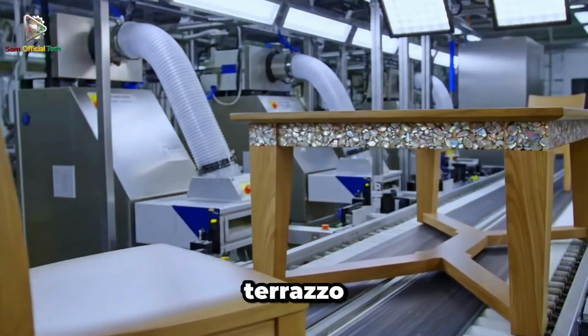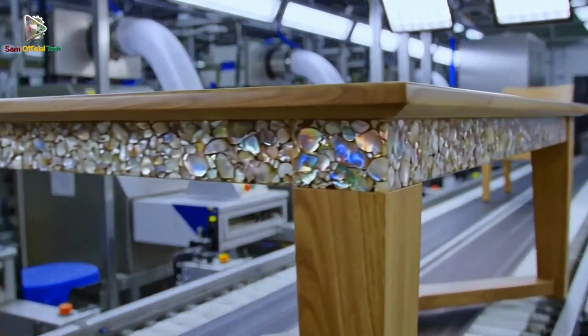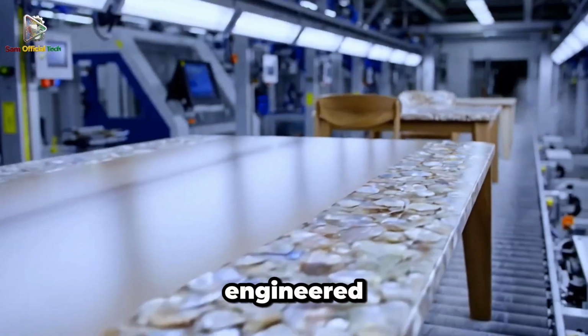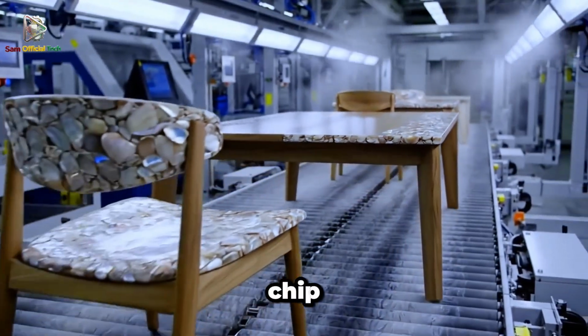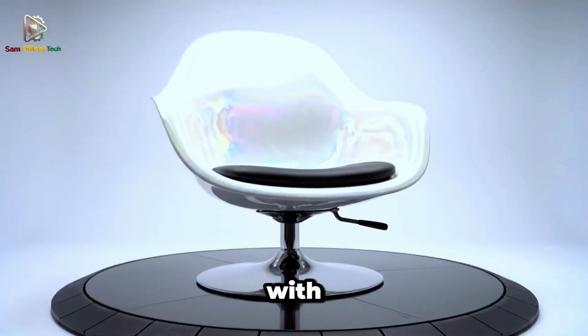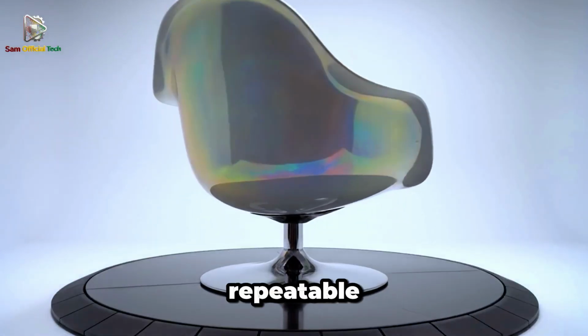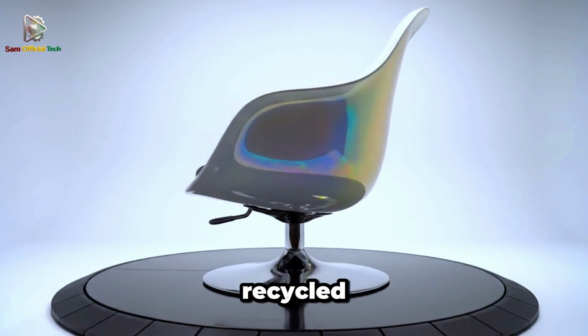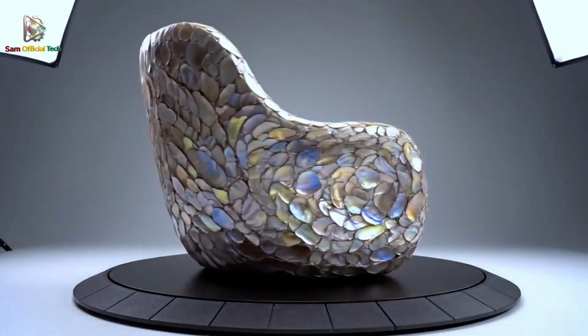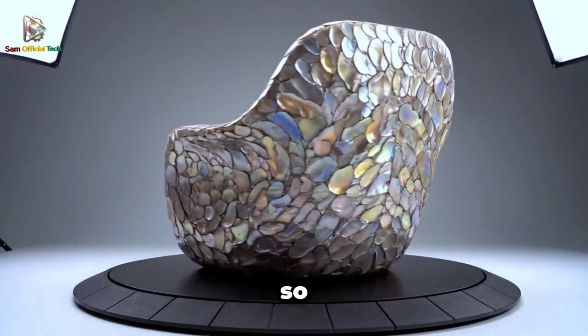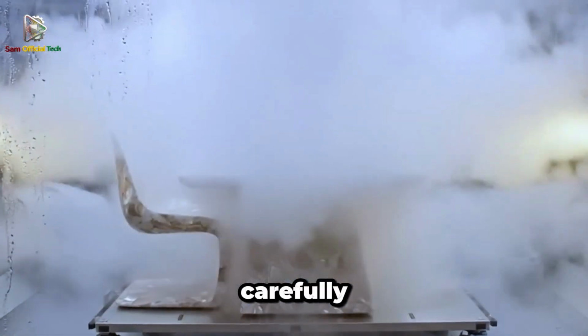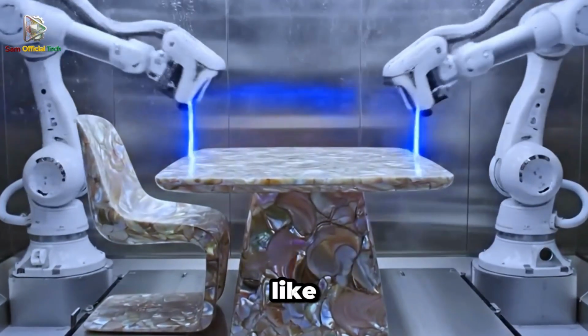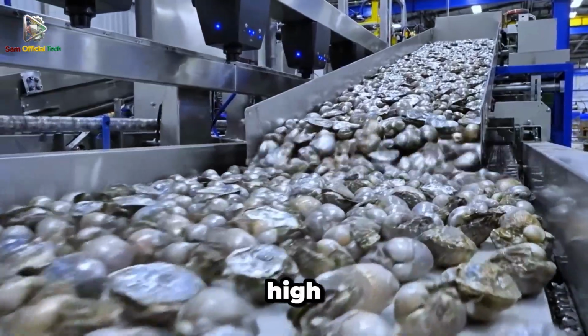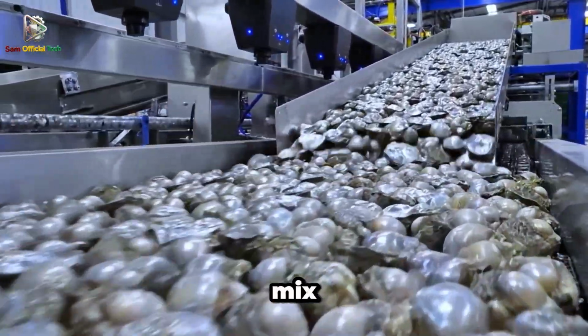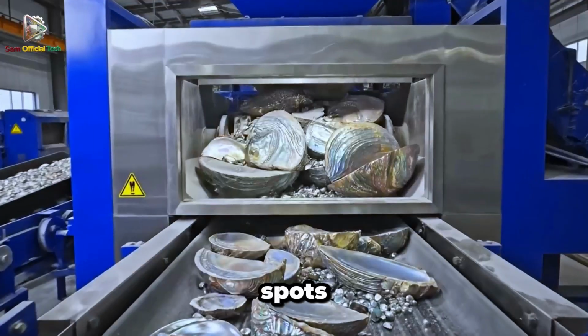If the product is a terrazzo-style seashell table, the shell chips are blended like an engineered aggregate. The plant measures chip size distributions, then mixes them with pigments and optional fillers to hit a repeatable look. Some factories add recycled glass or stone chips, but shells are the feature, so they control chip percentage carefully. Too low, and it looks like ordinary terrazzo. Too high and the resin can't fully wet the mix, causing voids and weak spots.